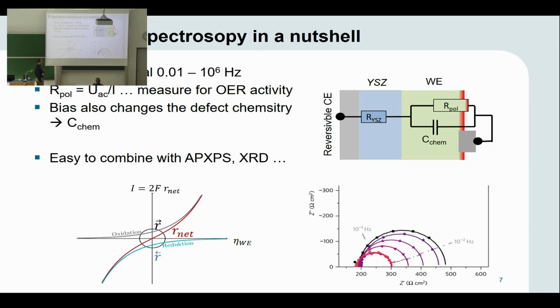And furthermore, due to the mixed conducting nature of the oxides that we investigate, the voltage also changes the oxygen stoichiometry. And also the altering of the oxygen stoichiometry gives a current as long as an AC signal is applied, and we can model this with a capacitor, which we call the chemical capacitance, which is a fingerprint property for the defect chemical state of the oxide.